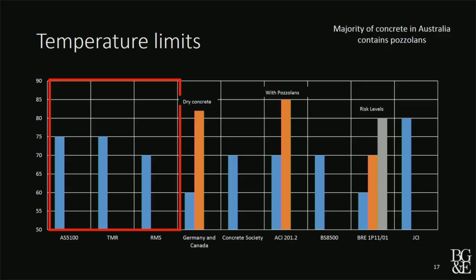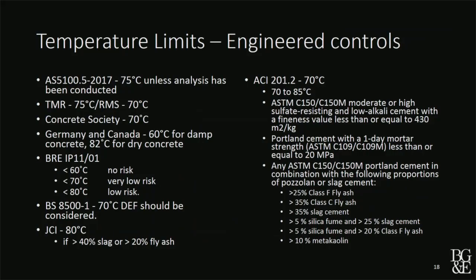How do you get there? You use ice, you might need to use cold water, you might need to cool your aggregates, but again, you may exceed those limits. A number of the different groups also allow increased limits if you have pozzolans in your concrete. And this is the approach that's been taken through ACI and also more recently through the Japanese Standards Institute, where they allow you to go to a higher temperature if you've got pozzolans in your concrete. So all the various limits are in the paper. I won't discuss them here. They're all available. But again, as you know from the research from Kelham, adding pozzolans to concretes basically eliminated the risk of expansion, even when the concrete was heated to 90 degrees Celsius.